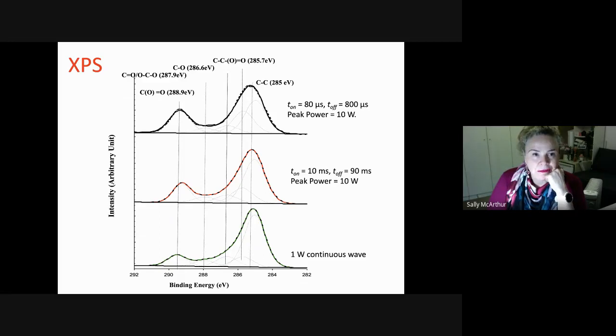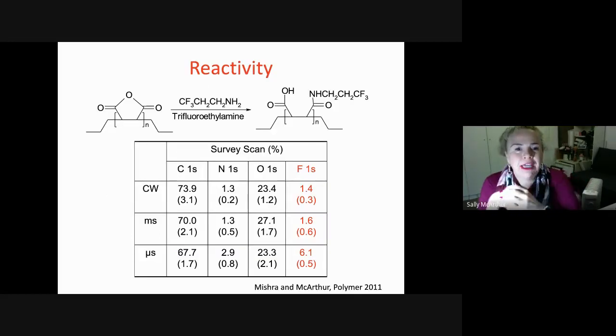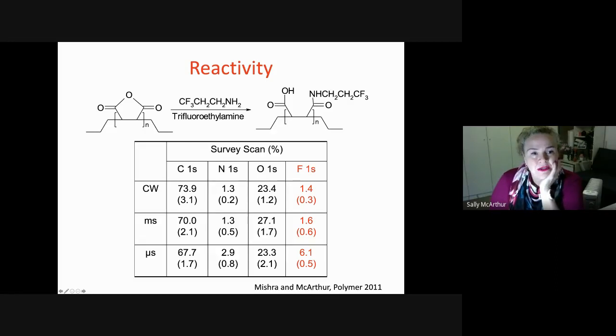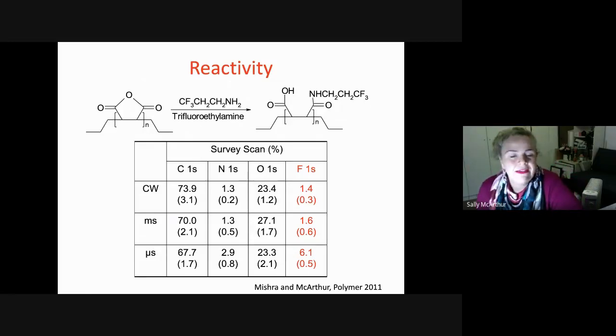Now, obviously, if we're looking at actually defining the difference between it being an ester species or an anhydride group on the surface, we need to actually look at its reactivity. And so we use trifluoroethylamine to actually react with the surface. It's done in the gaseous phase. If you react that species on the surface, if they're anhydride groups, you can get that to react, and you'll get a lovely fluorine tag on your surface. So you can use that amount of fluorine to give you an indication of how much and how many anhydride groups you've got on the surface with that ring opening reaction.